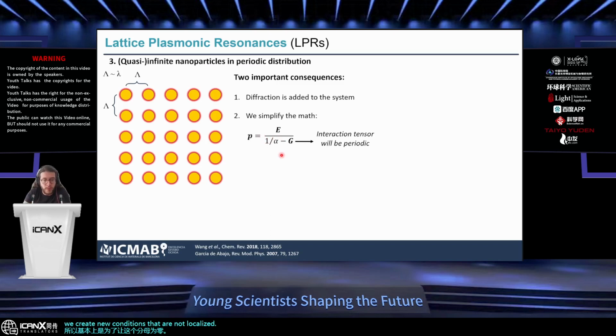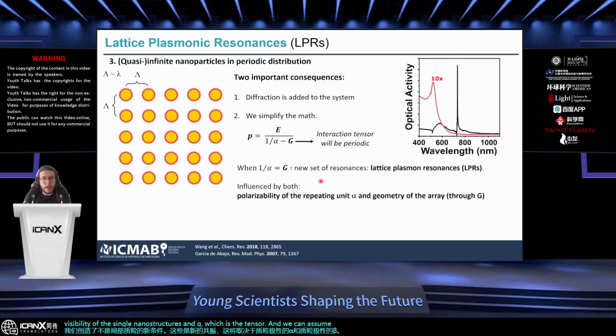These are new resonances, which will depend both on alpha, which is the polarizability of the single nanostructures, and G, which is the tensor. While alpha depends on the single unit, so it will depend on the size, the shape and the composition of the nanoparticle, G, as I just said, is considered to be periodic, so it will depend on the geometry of our array. The effect is very well exemplified in this plot over here, where you can see that you have a much more intense resonance, which is much sharper.